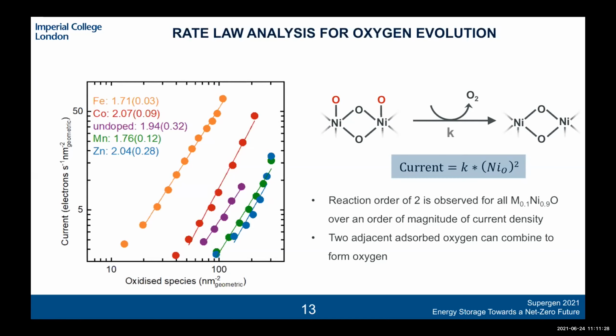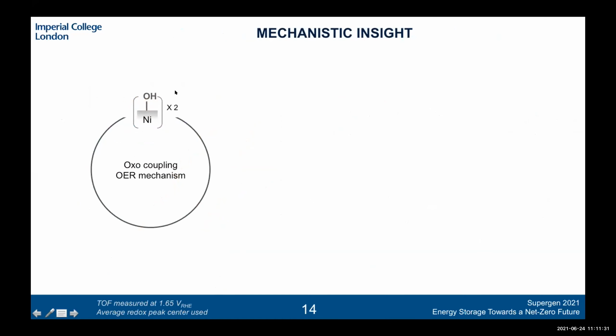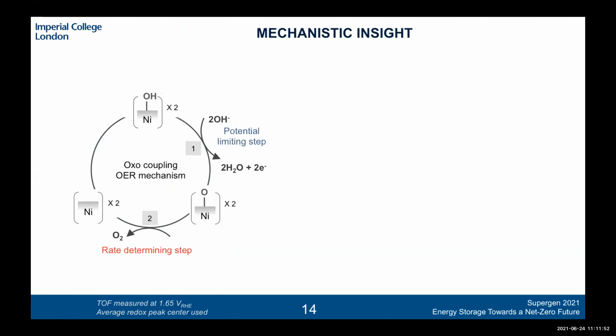And if we put all of that together, we can come to a concise picture, which looks something like this, where you have these hydroxide groups bound to a nickel center. As you increase potential, we see we have a growth of these oxidized species, which we've detected using UV-vis spectroscopy. So we are forming these oxo groups on the nickel center. And based on the rate law analysis that I just showed you, we can see that we need 2 of these different oxo species to chemically come together to form one molecule of oxygen. And that returns back a vacant nickel site on which you can again find OH- groups from solution and continue the catalytic mechanism.